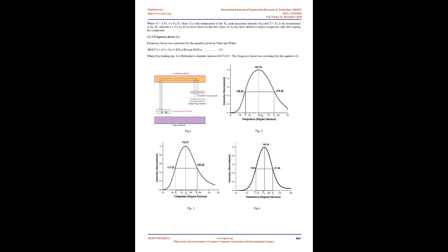For kinetic and trap depth analysis, TL glow curves were recorded at a heating rate of 5 Ks^-1. All the samples were exposed to a low dose of 5 Gy. The measured glow curves were analyzed to resolve the individual peaks, assuming first order, second order, and general order kinetics. The order of kinetics and activation energy of the isolated peak were found using Chen's set of empirical formulae. To determine the order of kinetics, b, the symmetry factor given by Chen was used [24, 25].